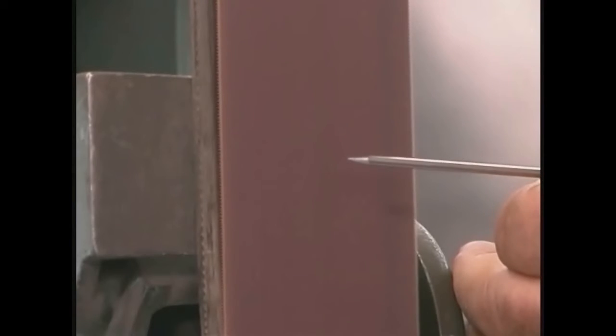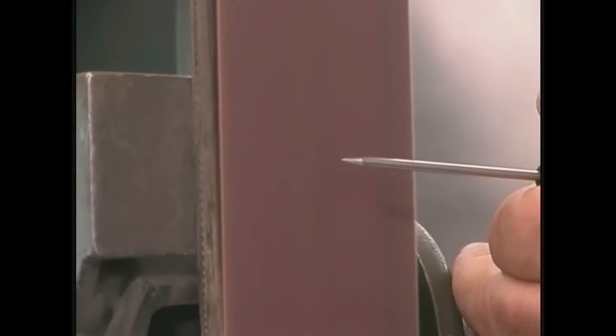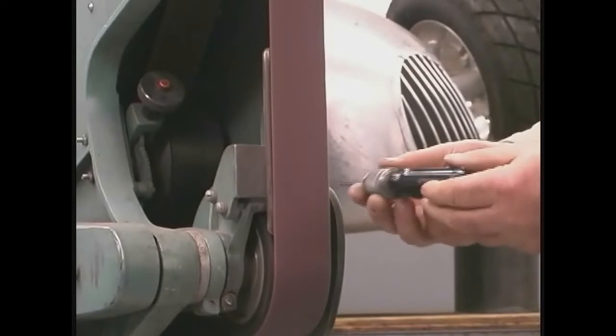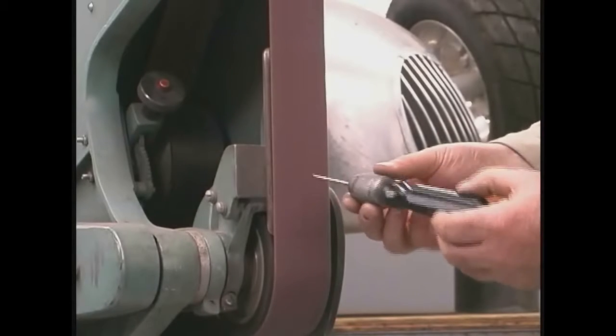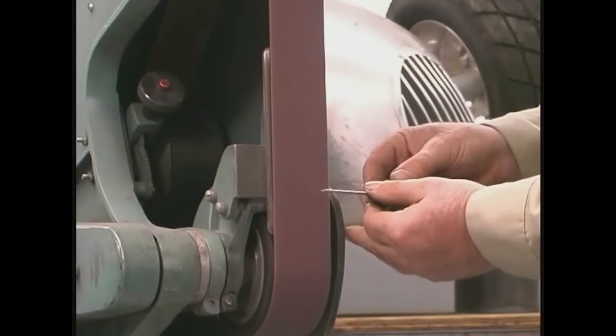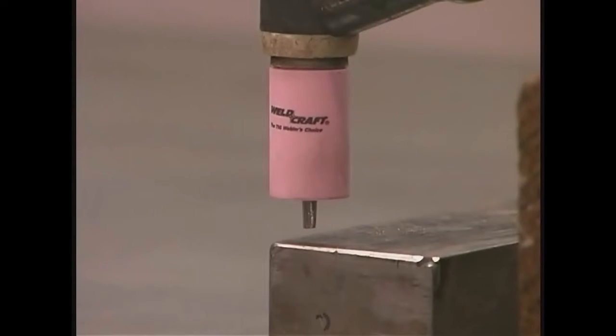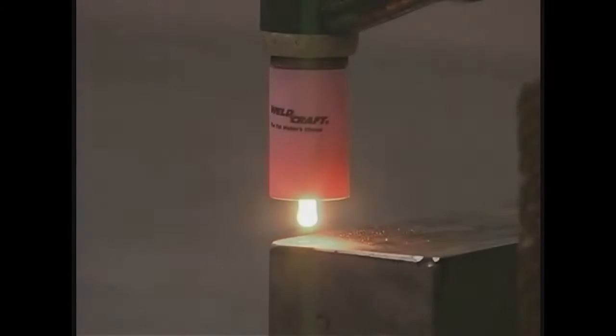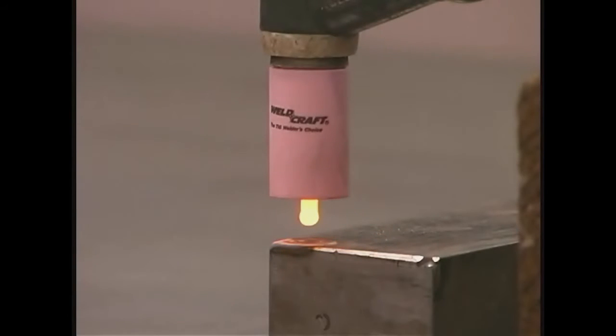For welding thin stock at low amperage, a needle-sharp electrode really helps to focus the arc tightly. For high current work, having a tiny flat on the tip of the electrode will help keep bits of tungsten from spitting into the weld bead, causing contamination. For anyone using pure tungsten in a non-inverter machine, the proper preparation is to put a ball on the end of the tungsten by running a burst of DC positive current through the electrode.